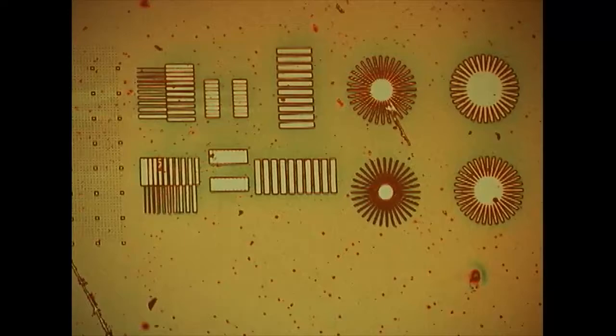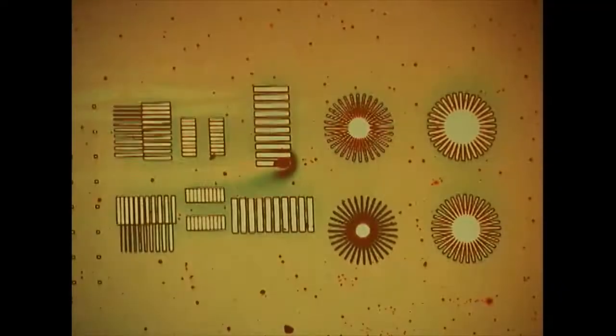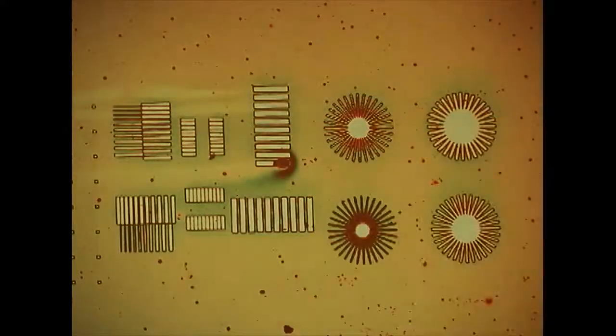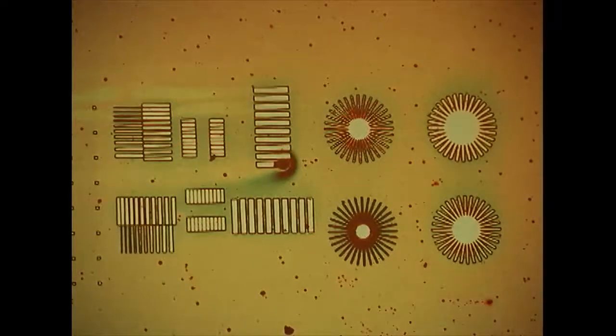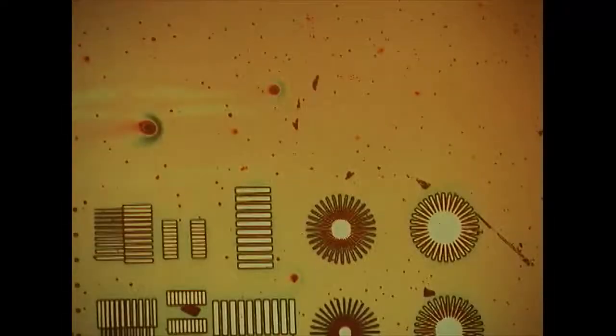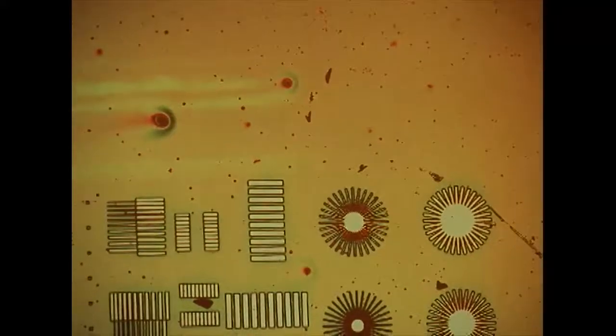So we go ahead and count 100% of half speed, 90% of half speed, 80%, where we can see that we're just on the edge. And finally, if we roll back to 70% of half speed, we can see that our gaps are nice and uniform, and this is indeed the ideal condition. If we move down to 60%, we can see that this is also a good value, something we certainly can use, but we start running the risk of being underexposed, where there's residual material left within the feature.